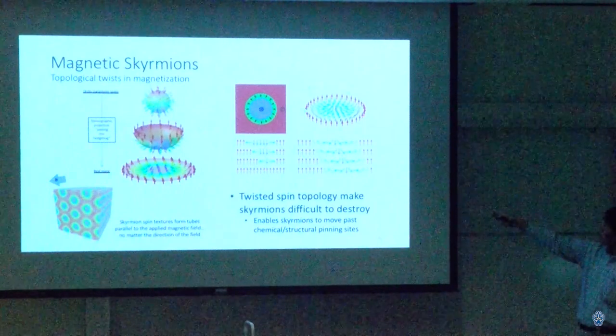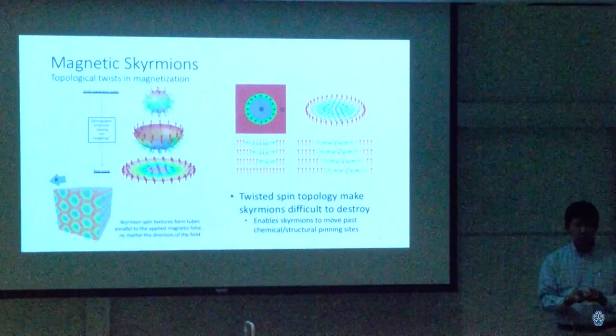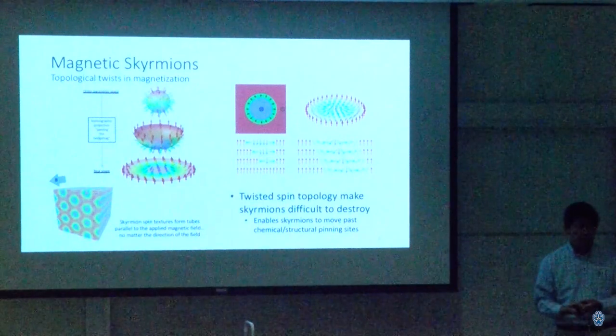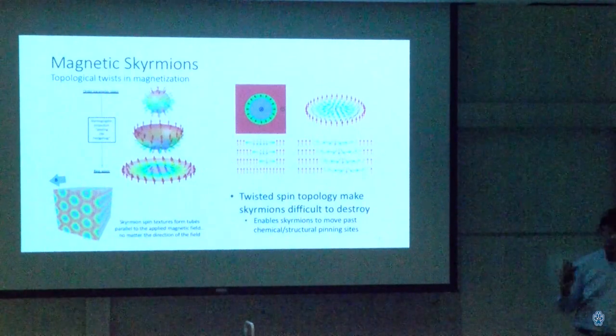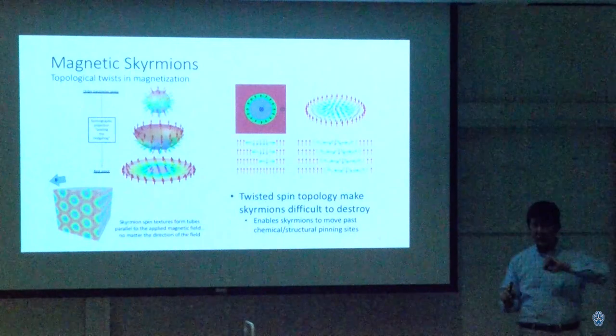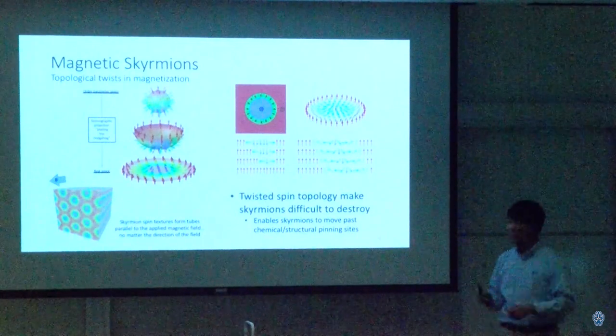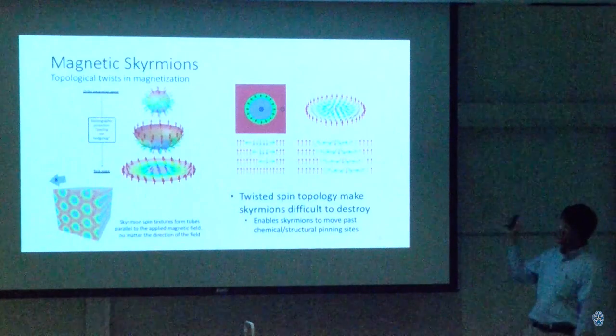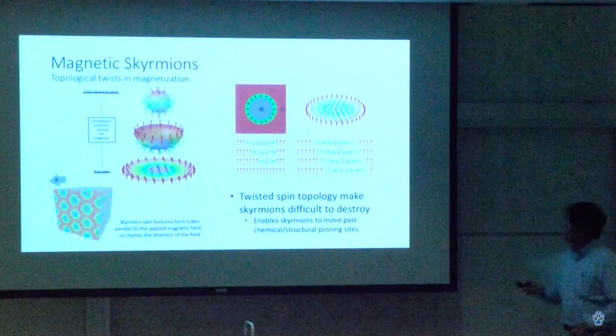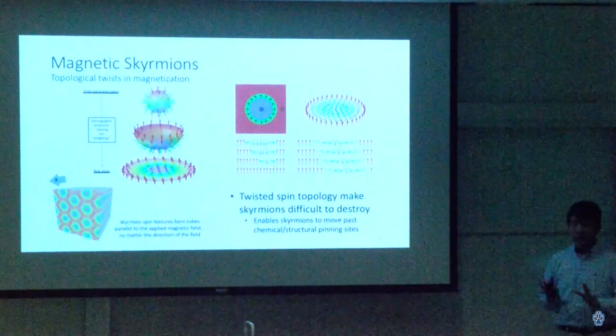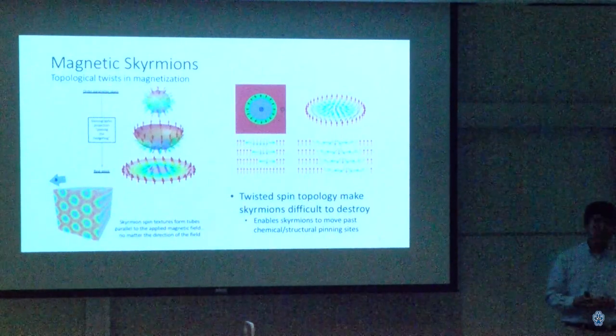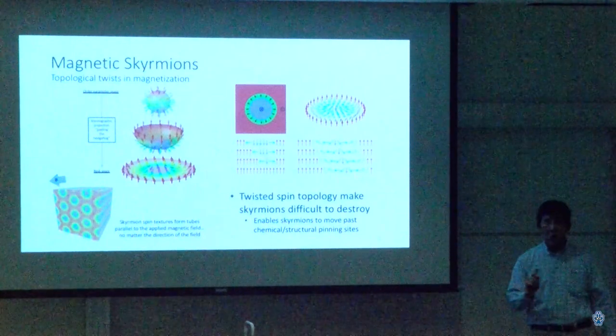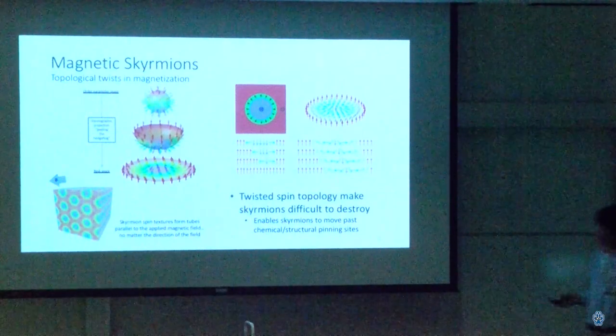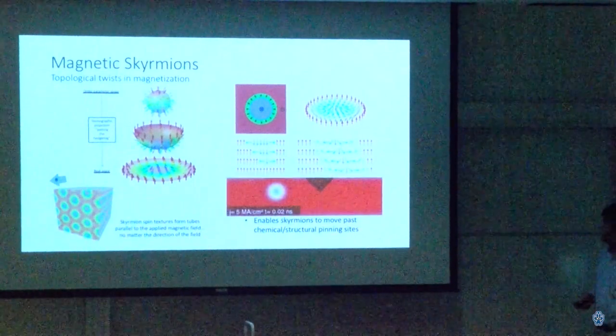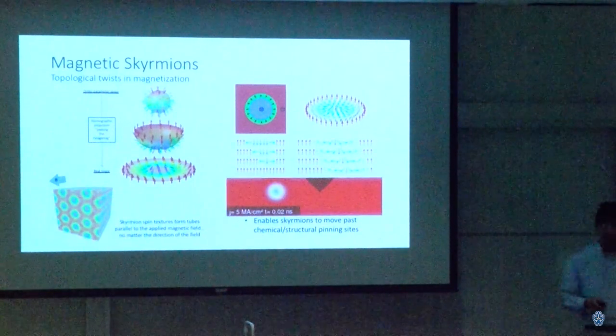On the other hand, because a skyrmion requires spin exchange as well as spin-orbit interactions to exist, if I try to rotate one spin, it just causes all the rest to stiffly rotate in response. So if I twist a spin trying to get it to disappear, it just shifts to the left, or in this case, to the right. This reveals one of the important features of a topological magnetic defect. It's extremely difficult to just make it go away from small changes to the magnetization. And that has potential practical applications.